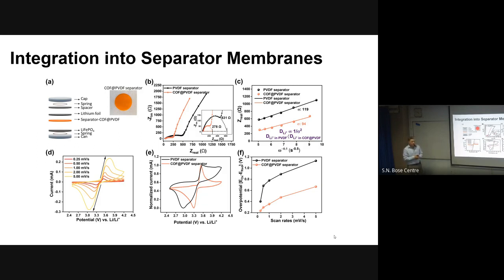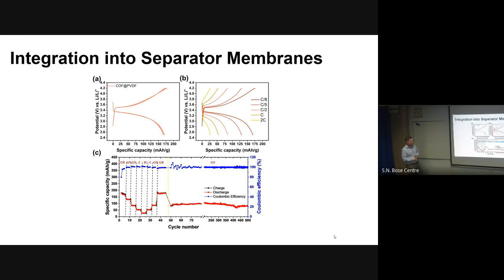Of course, if you look at commercial lithium-ion batteries, we use completely different separators, Celgard based on PP with much larger pores, and those values are not really comparable. But we just wanted to see the benefits of exfoliating. And we also see the overpotential is much lower as we don't have any COF inside the membrane. We could run this battery for roughly 500 cycles. It was stable. This is a small proof of concept, but we are not challenging current batteries.